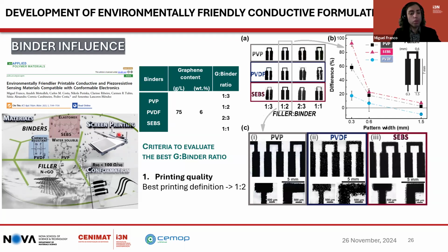But small amounts of stabilizers are very important, because if you have a mismatch in surface tension, you can have very poor printing resolution. If you want to achieve high resolution, you need to make the best formulation possible. So you need to take into account factors like surface tension, foaming or defoaming. The formulation itself will use a mixture of several stabilizers. This is more relevant in inkjet printing.